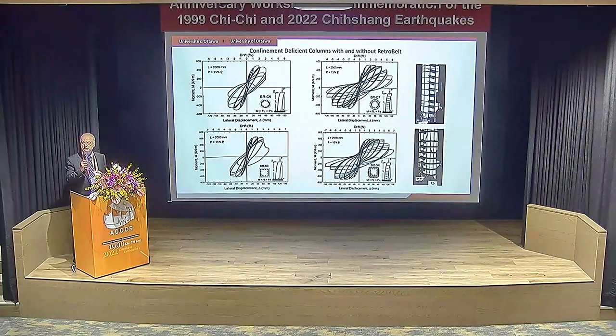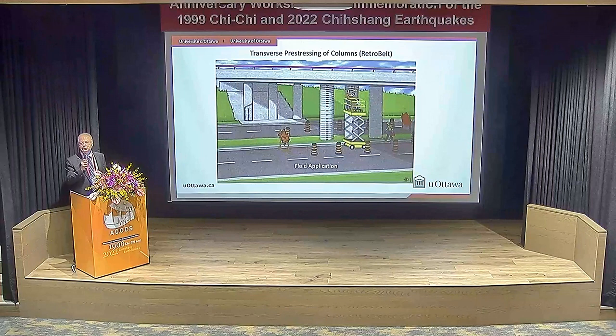Now, these are the comparisons for flexure deficient, confinement deficient, flexure dominant columns. And similarly, if there's no retrofit, and these are the columns that have about a foot spacing between hoops, like 300 millimeters spacing. And of course, reinforced concrete has a little bit of inherent ductility. We were able to go up to 2% drift under low axial loads, and that has improved up to 4% by the time we applied Retrobelt. This is our artist's view of how to apply it in practice.